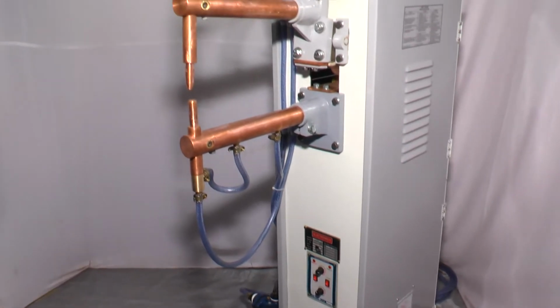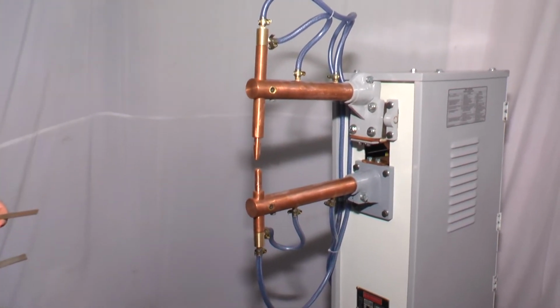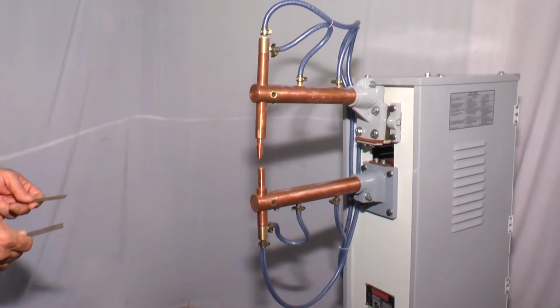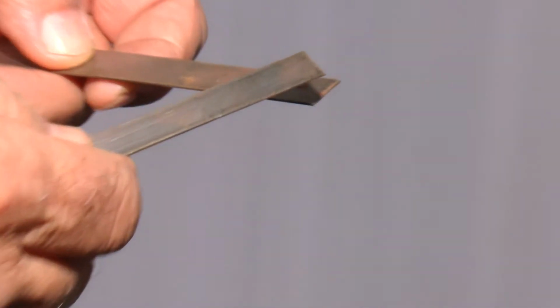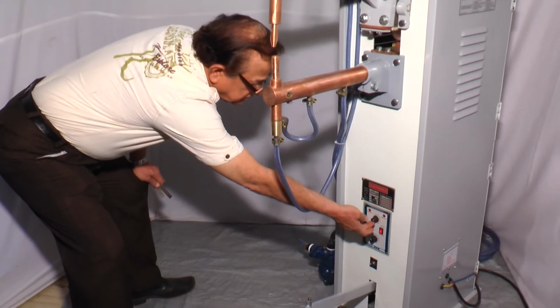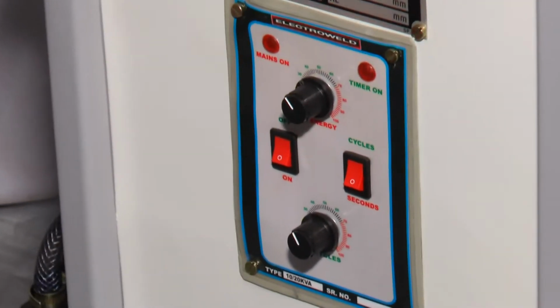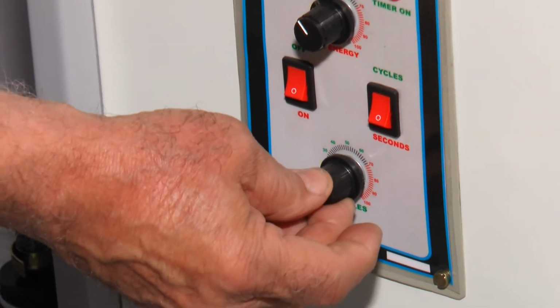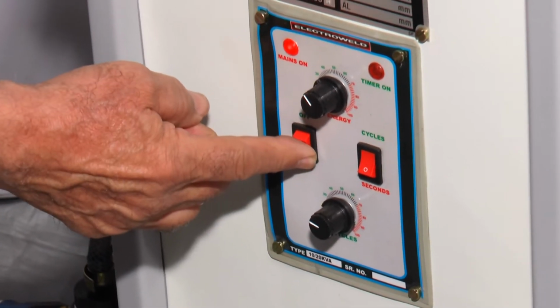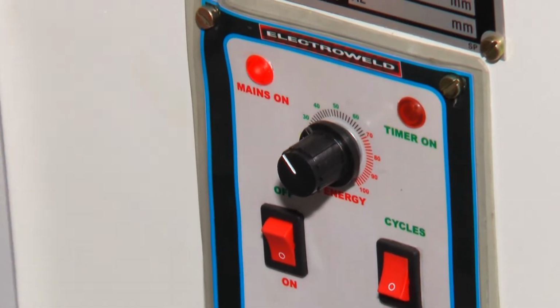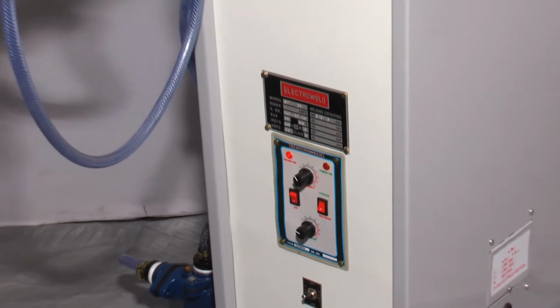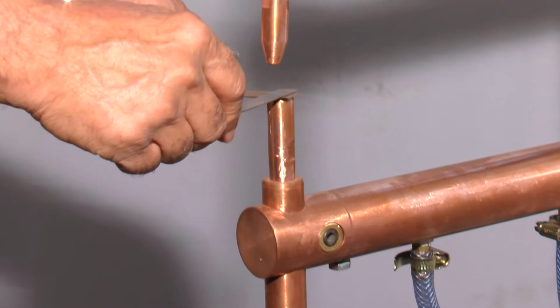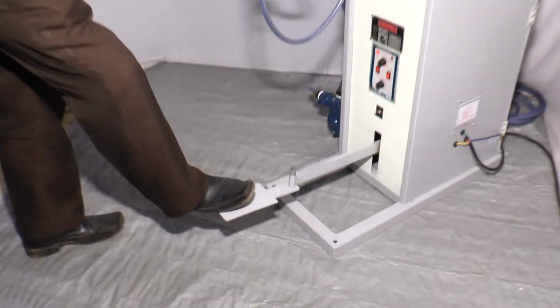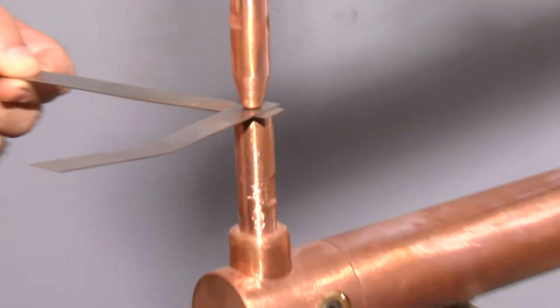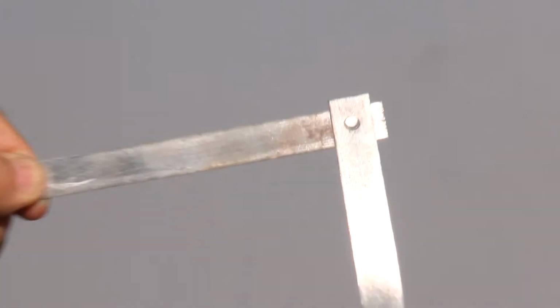Now we will show the welding of the strips and components on this 15 kVA Electro-Weld brand spot welding machine. Supposing you want to weld 0.5 plus 0.5 mm thick MS components like this, then kindly arrange the power control, say at number 30% of the heat, the weld timing say about 10 cycles, and switch on the timer switch. You will see the mains on light will indicate. Now we can put the two sheets in between the electrodes and press this pedal fully. You will see the welding will take place and the current cutoff will take place automatically. See, this is how it is spot welded.